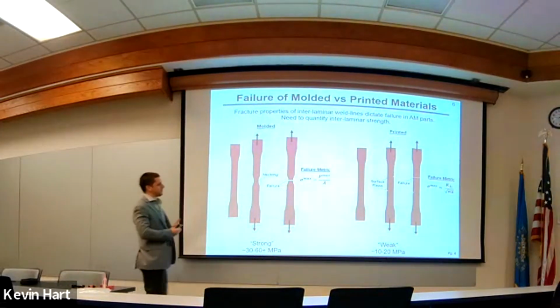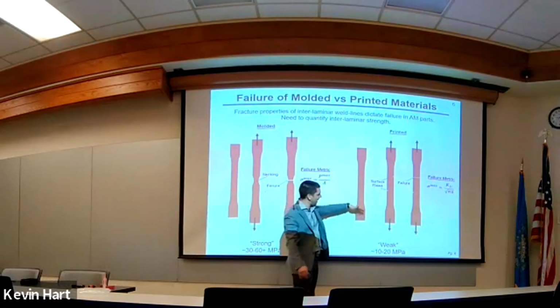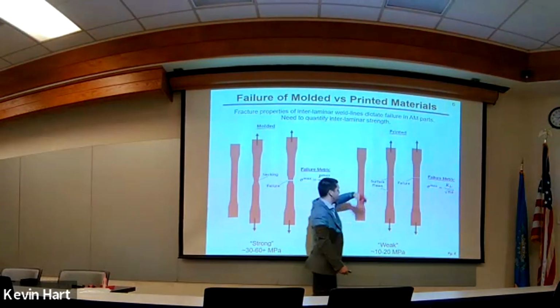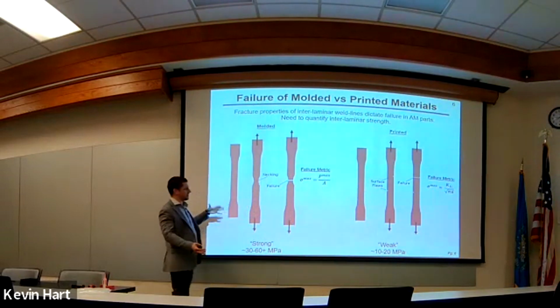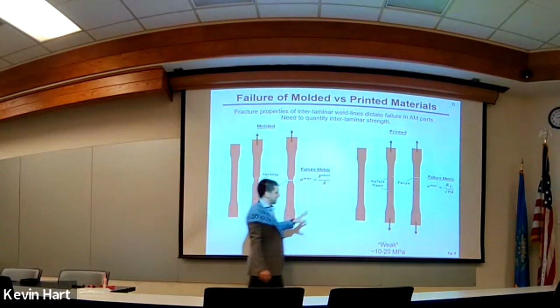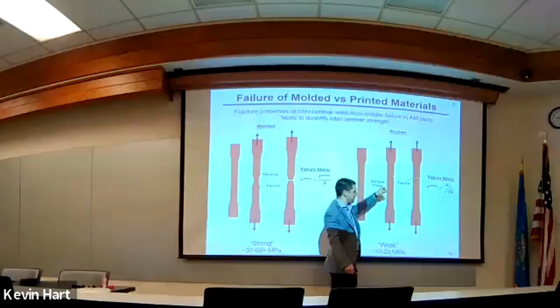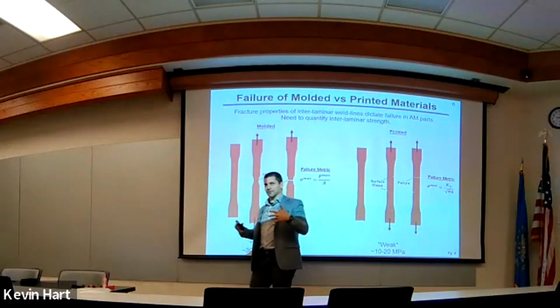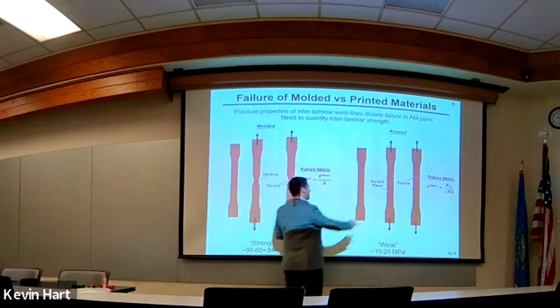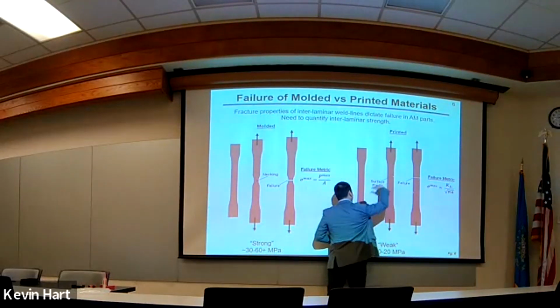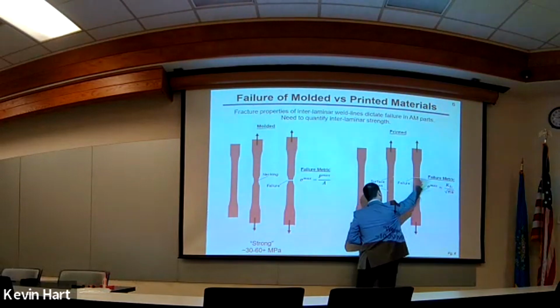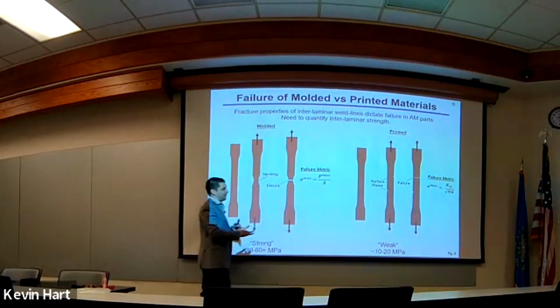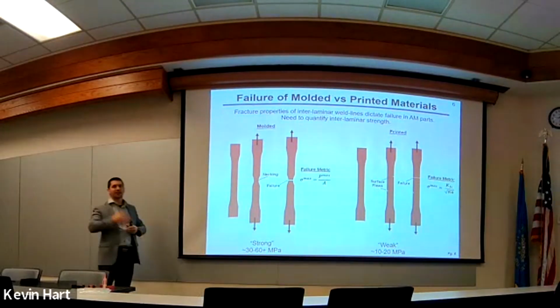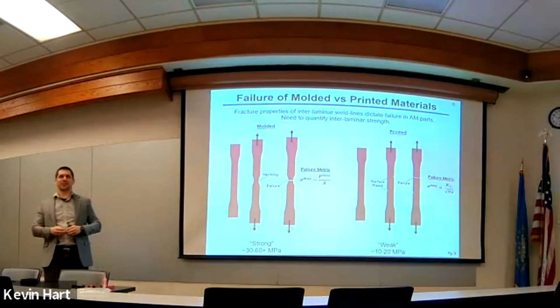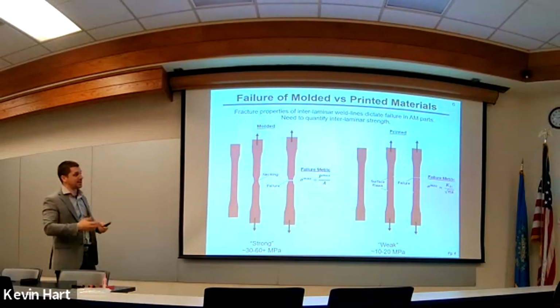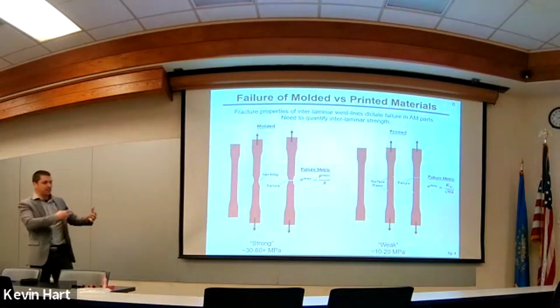But 3D printed objects, especially ones that have this rastering pattern and this layering across the direction of loading, they're not really governed by failure of the material. There is a little bit of that going on, but most of the time they fail prematurely because of the ridges on the side or internal surface flaws that cause stress concentrations and stress intensity at the edges where the surface flaws are, that just propagate through the material and break it in half a little bit more quickly. And this whole idea of a notch or a crack inside of a material that causes propagation of that crack to get the material to fail, this is getting into the realm of fracture mechanics.